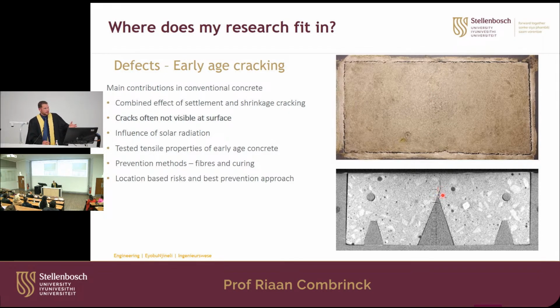And then often when the concrete starts shrinking due to drying shrinkage after 7 or 8 days, this crack just opens and everyone thinks, okay, well, this is a drying shrinkage crack. But it's actually a plastic shrinkage crack that was opened much earlier.